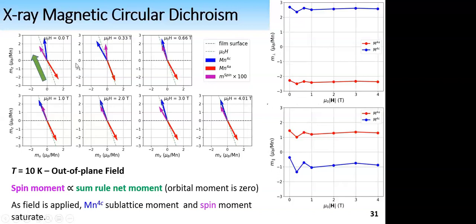The sample was saturated before the measurement. Then as the field is increased, we would expect the 4C sublattice to basically saturate along the field. And this is exactly what happens. Now, something important to notice here is that indeed, there is a small non-collinearity between the two magnetic sublattices. So this is our direct observation of non-collinearity of sublattice moments.